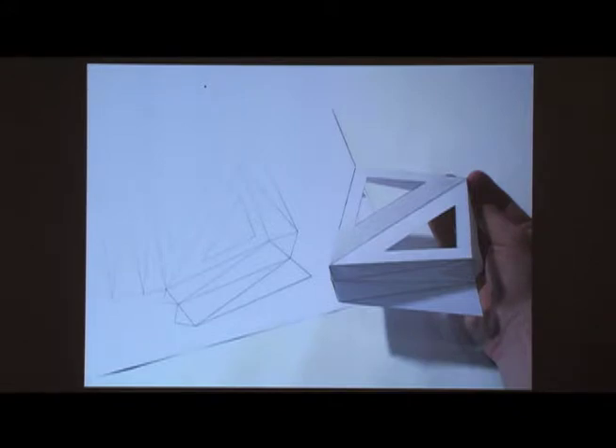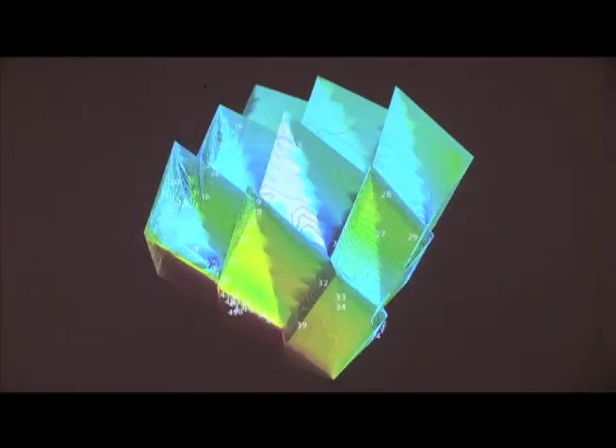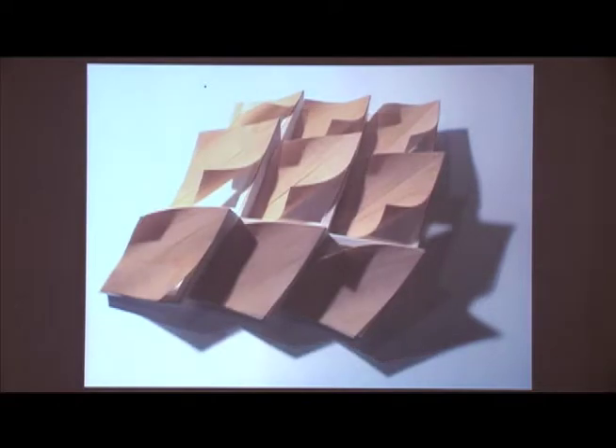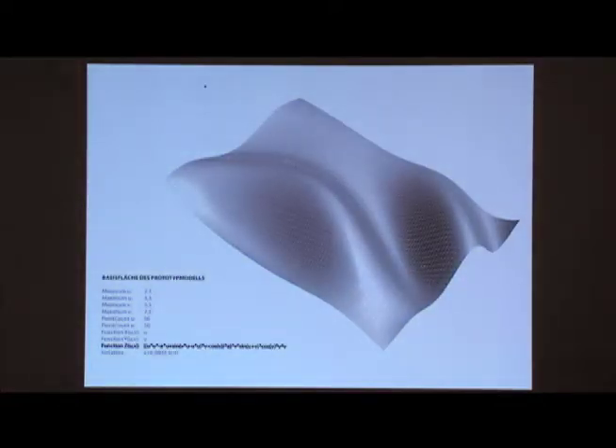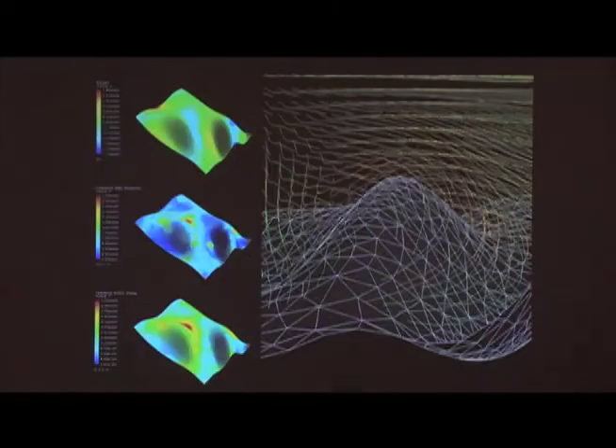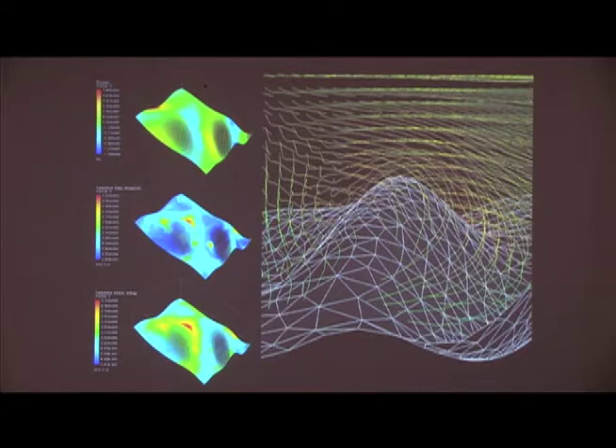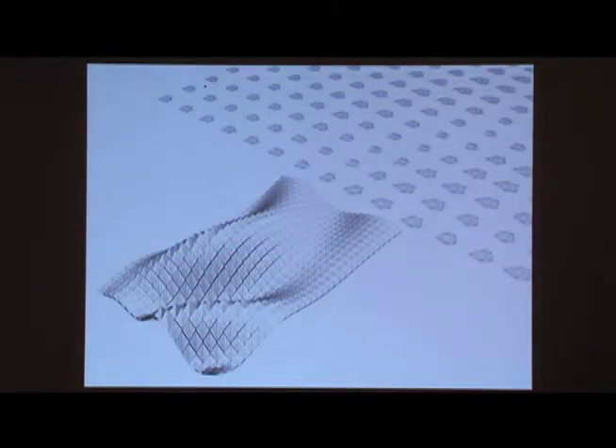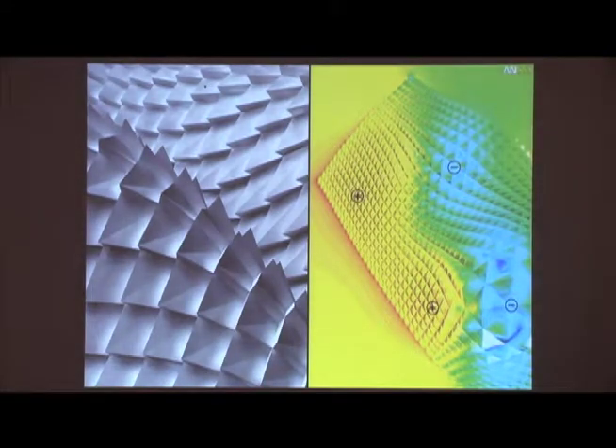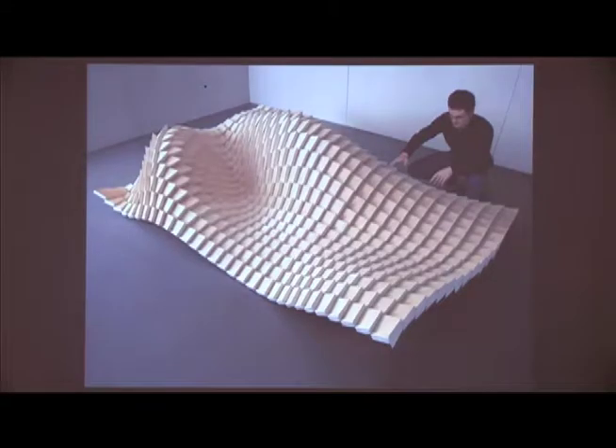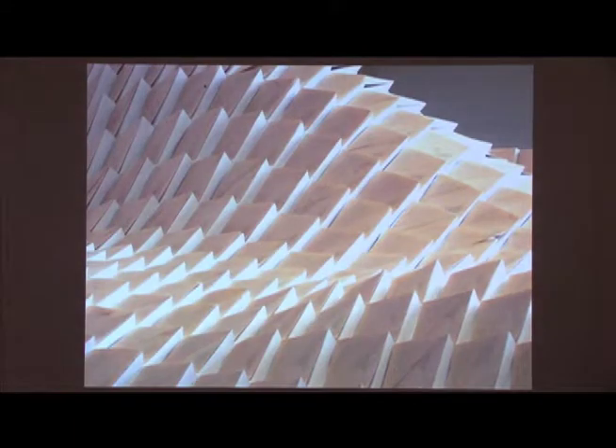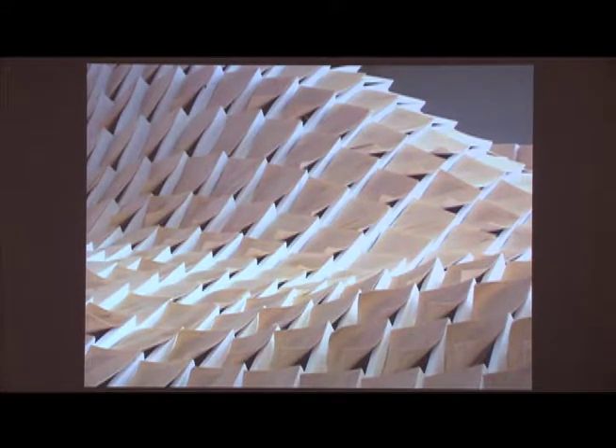So we then went on to design a substructure for that, which is a simple folded one-cut thing. We looked at the interdependencies of the thermodynamic influences on the distribution of moisture in relation to the morphology of the system, developed a set of components from that, used a mathematical equation to drive the subsequent surface evolution, which happens in constant feedback with thermodynamic and structural analysis, which led us to this prototype, which, despite the high level of articulation, we could build immediately as a functional artifact, which actually changes its porosity with changes in relative humidity.